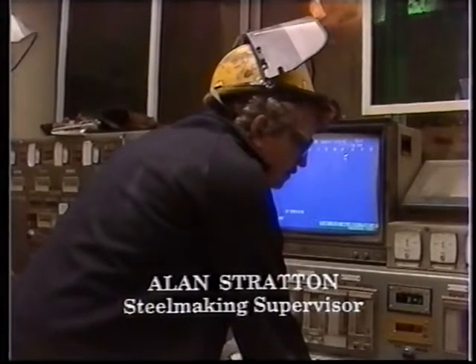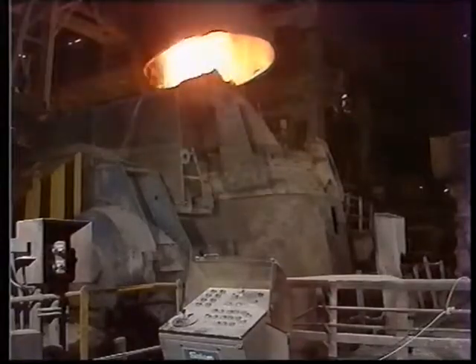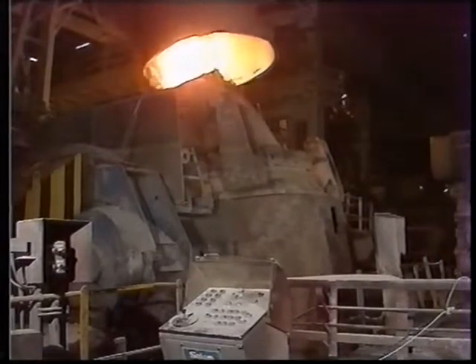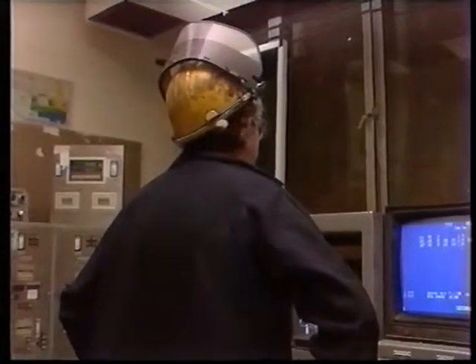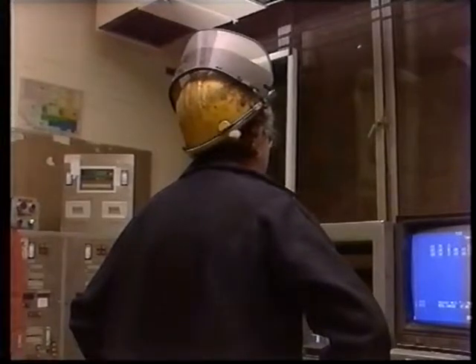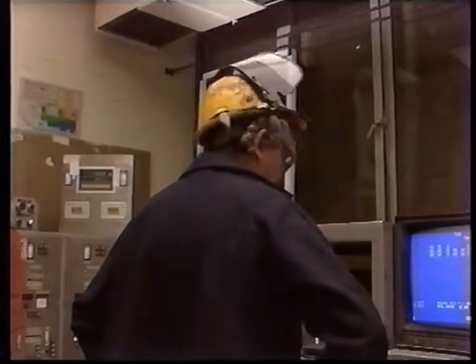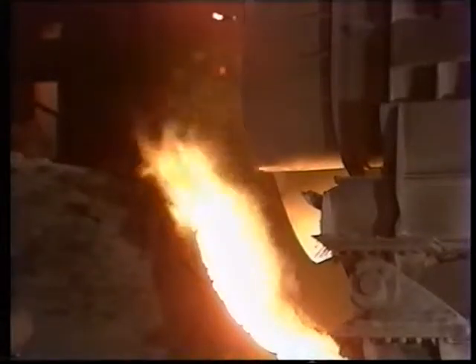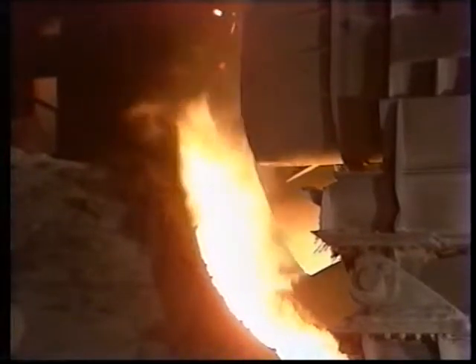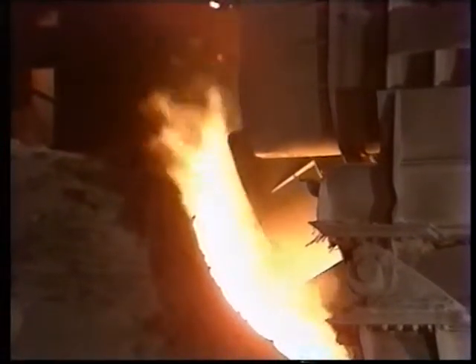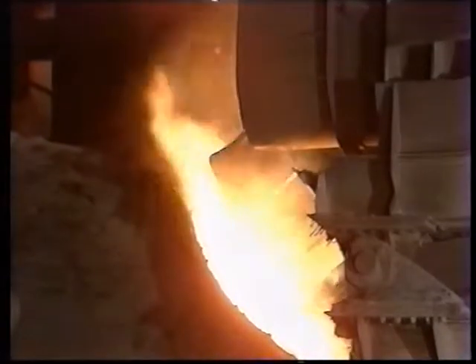This is the AOD control room. The molten metal from the arc furnace is transferred into the AOD vessel, where we refine it to meet the customer's requirements. We inject oxygen and nitrogen or argon into the molten bath to reduce the carbon content. The oxygen also increases the bath temperature, which we control by making various coolant additions.